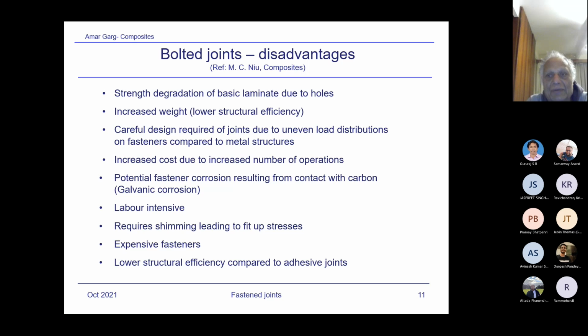And I'll show you one chart where I would say for bolted joints, the maximum efficiency for a composite bolted joint around 40 to 45% is possible. If you have aluminum to aluminum fastened joints, you can go up to 70% efficiency. And bonded joints, you can achieve almost 70% efficiency, could be more. So that way, the bolted joints in composites, that's one of the disadvantages. The joint efficiency is low. And we'll discuss why so. Careful design of joints is required due to uneven load distributions on fasteners compared to metal structures. That also we'll discuss.